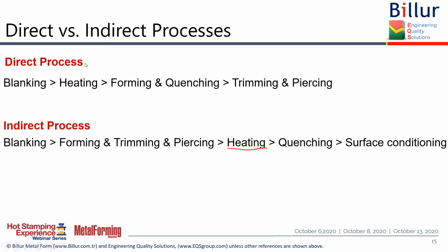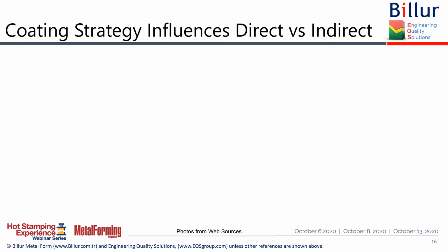And you might have heard 2 different names for direct and indirect process, especially in German language and translations from German. You might have heard press hardening. This is what we use also for PHS. And there's another word called form hardening. I have been to a handful number of lines, and I have only seen 1 form hardening line until now. So around the world, we can say maybe 95% of the lines are for direct process, maybe 5% only for indirect process. That's why we don't say form hardening steels.